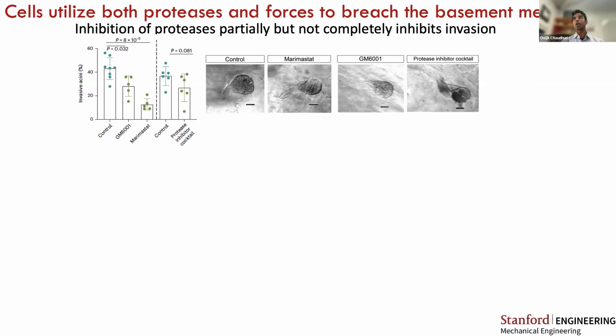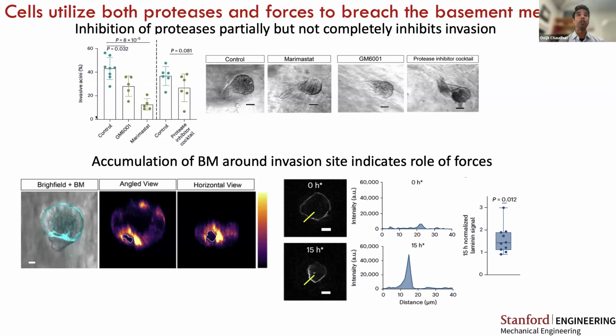Okay, so now that we had this 3D culture model, we sought to understand what are the mechanisms driving this collective invasion of the basement membrane. So we first looked at proteases. We inhibited protease activity using broad spectrum protease inhibitors. And we see there's a reduction of invasion, but invasion wasn't completely abrogated, suggesting that proteases are involved, but they're not strictly required for invasion to occur. And indeed, if we looked at the signal of the basement membrane around the invasion site, we see that it's higher and densified, consistent with the idea of cells using forces to open up the basement membrane, in which we expect the matrix and basement membrane to be densified around that site of invasion.